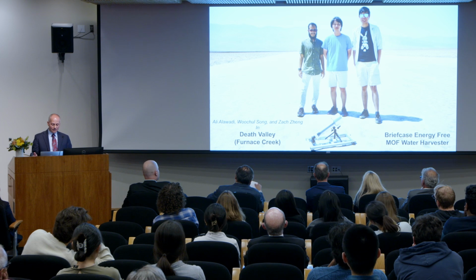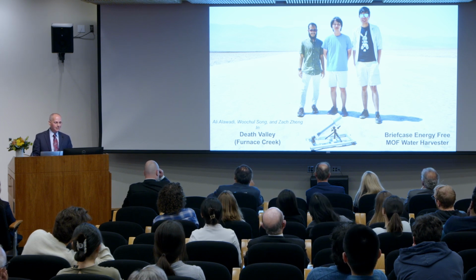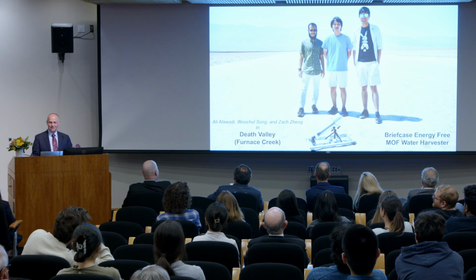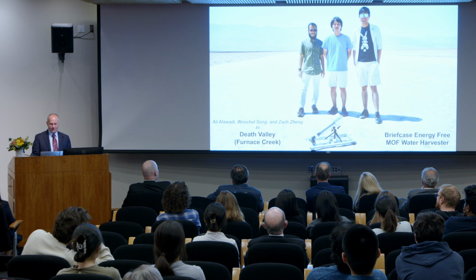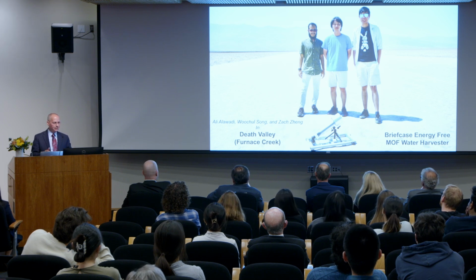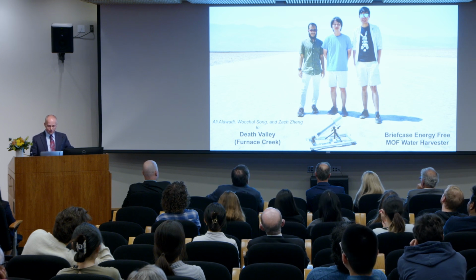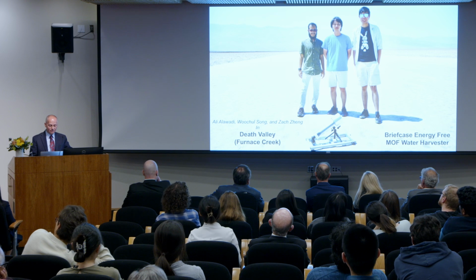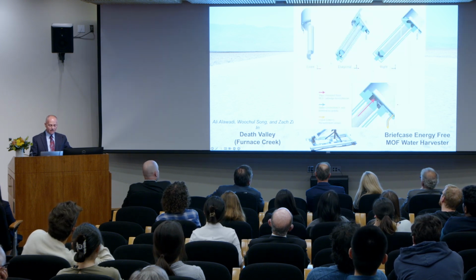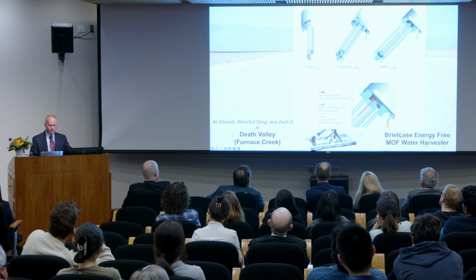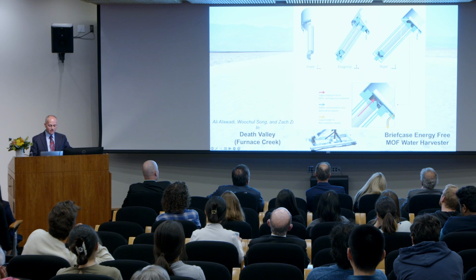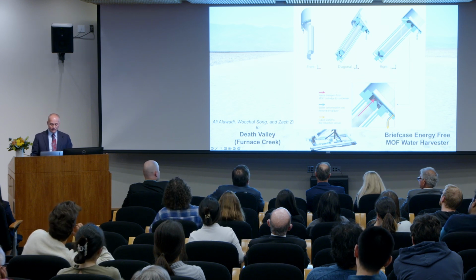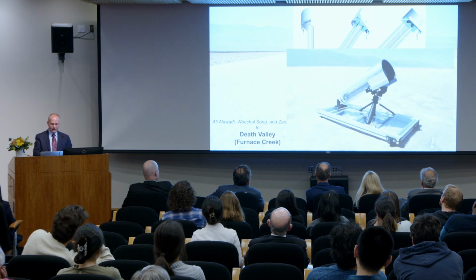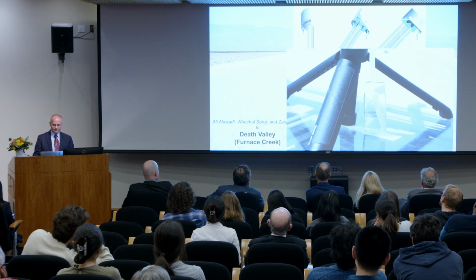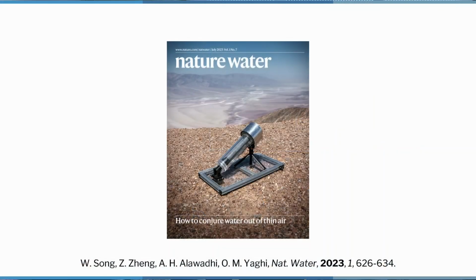And so my students are real heroes because they inspire the professor. We always think that we inspire the students, which is true, but very often they inspire us. And so they volunteered to take this MOF to the driest desert, Death Valley in Furnace Creek, a very beautiful place, very dry. And this device had pancakes. We designed the MOF into pancakes to maximally expose them. During the night, it's exposed to water in the air. During the day, you close it and it heats up, and you can collect water from the Mojave Desert. So this is the device sitting there overlooking the Furnace Creek Valley.